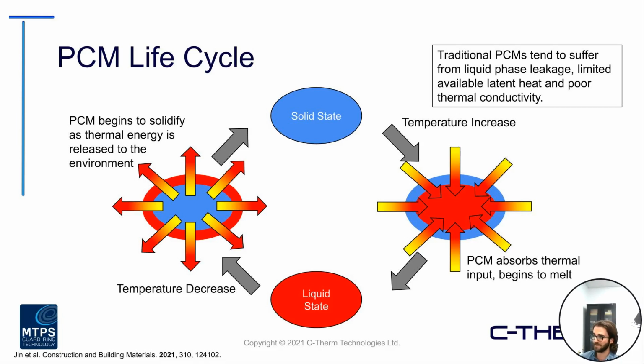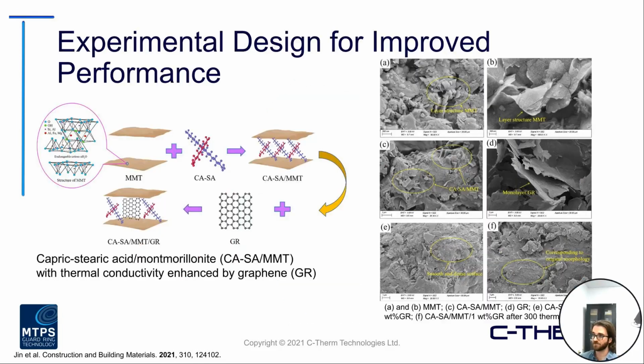However, traditional PCMs, while they do have these very unique qualities, tend to suffer from liquid phase leakage, limited available latent heat, and generally poor thermal conductivity. So what these researchers were aiming to do is improve the overall performance of this capric-stearic acid, which was their PCM, using a montmorillonite substrate to act as basically an encapsulant to help contain that PCM during the transition. On top of that, they wanted to incorporate graphene to enhance the thermal conductivity of this sample. So it was twofold: to reduce some of the leakage effects and also improve the thermal properties.